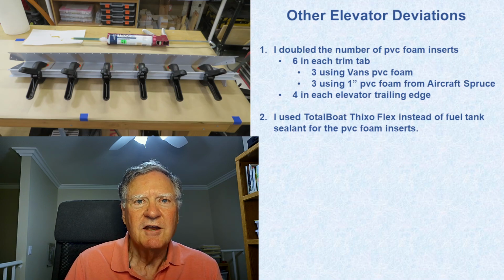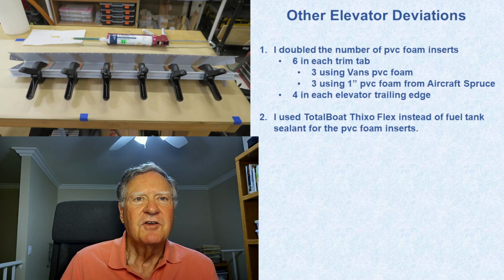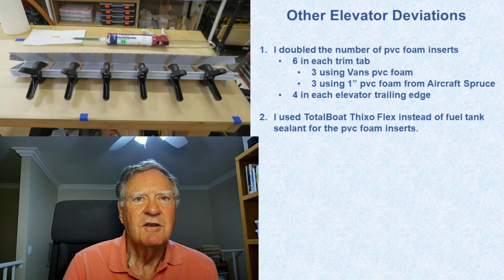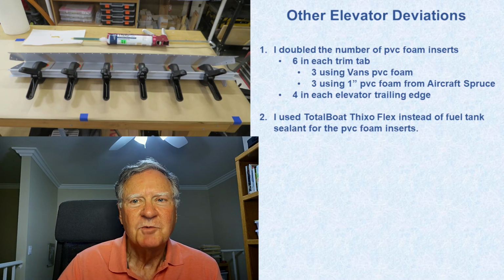Basically, what I did was an aluminum to aluminum peel test. So I take 2 pieces of aluminum, each is 16 thousandths thick, and I glue them together, 1 square inch, basically. And then I measured the strength that's required to peel them apart. And I tested a bunch of different adhesives, and this one was the strongest of the bunch. So I didn't just throw a dart and pick this one randomly. I probably tested 20 or 25 different adhesives, and this one was the strongest. It's less flexible than fuel tank sealant, but more flexible than normal epoxy.